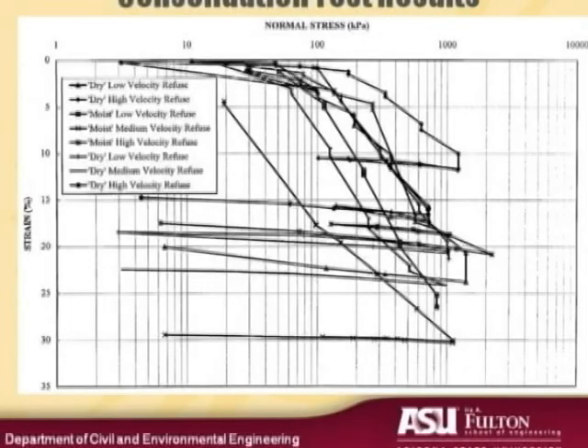These are the consolidation test results. A little bit all over the map. The one thing I'll point out is that on unloading, there's very little recoverable strain. Most of the strain in loading is irrecoverable. So we do the loading and then the unloading cycle, and you can see from those bottom plots, very little vertical strain on unloading.